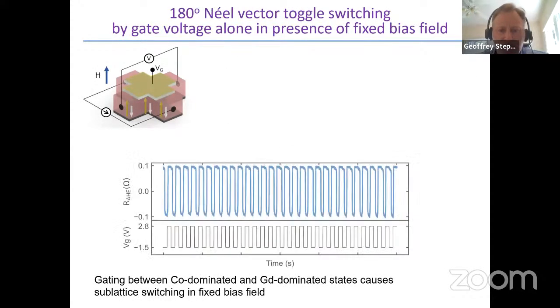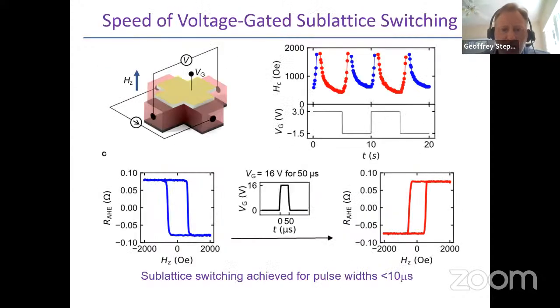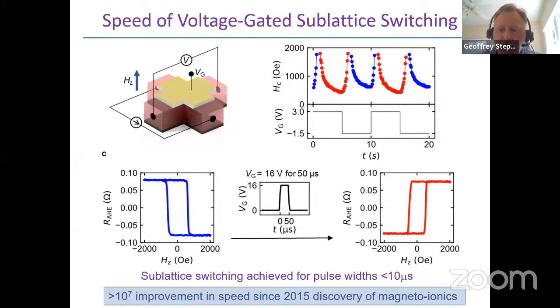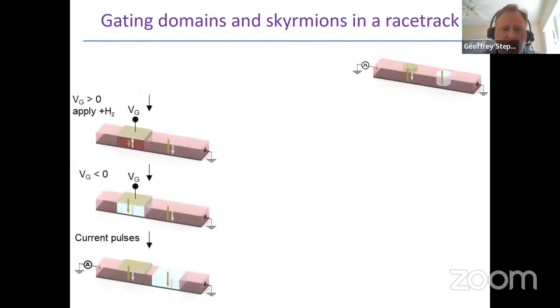So let me just skip through this one. So we've achieved, with relatively large voltage pulses, switching of the sublattices at speeds of the order of 10 microseconds, which isn't fast on the scale of spin orbit torque switching, but in terms of ionic devices, since the discovery of this nascent subfield magnetoionics in 2015, this is a factor 10 to the 7 improvement in speed. And in terms of energy, well, let me show you the skyrmion first.